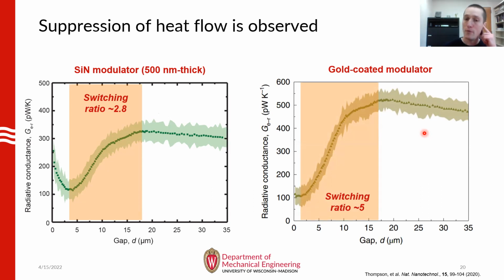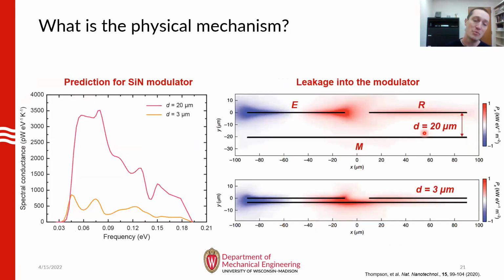So what's the mechanism here responsible for this switching effect? If you look at the plot on the left, this is the computed spectral conductance between our emitter and receiver as a function of frequency. Initially, with a large vertical offset of 20 micron, the spectral conductance is peaked near a frequency of 0.075 electron volts over here. That corresponds to a wavelength of around 16.5 micron.